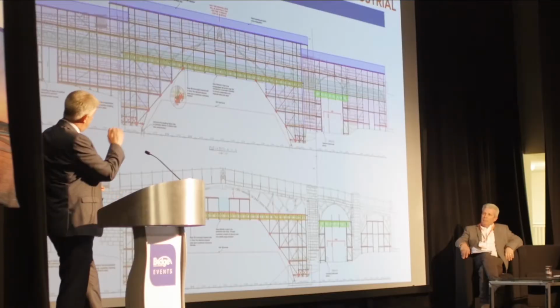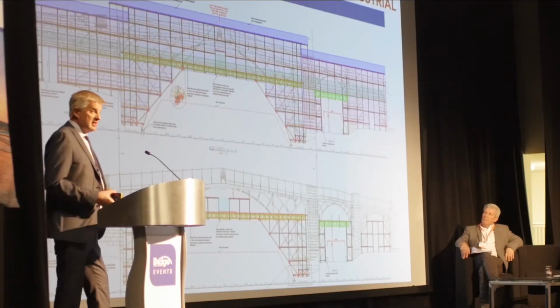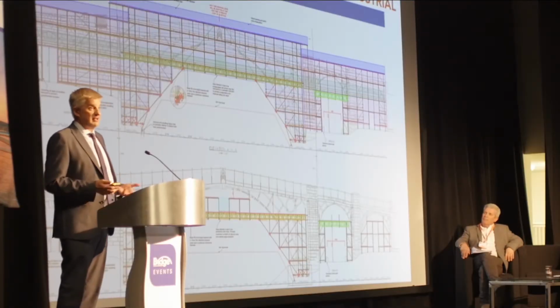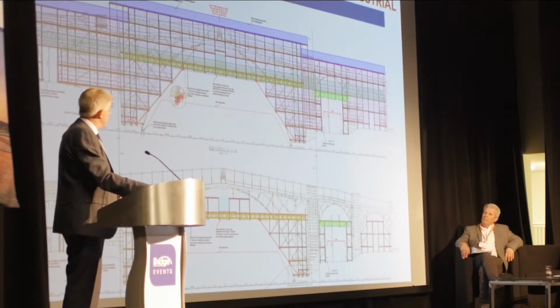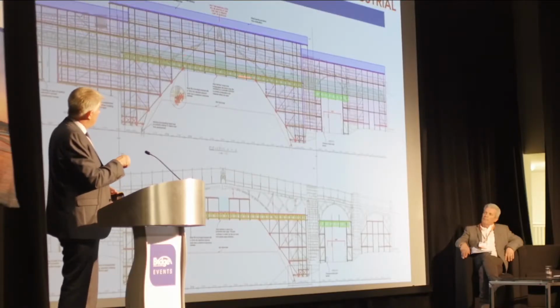The first key thing for ourselves was obviously the temporary works, and we had to take that up to the full design. The clear span itself is 30 metres, and obviously we had to reduce that down to the capacity of the unit beams, which was around 18, so we did that via a staged approach, but we couldn't actually impose any loads on the brittle cast iron structure itself, so we actually had to build everything up from beams at the base, and then obviously staggered up so that we allowed to get this unit beam across.